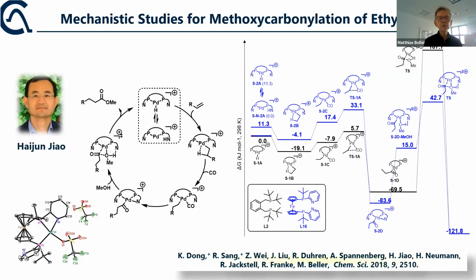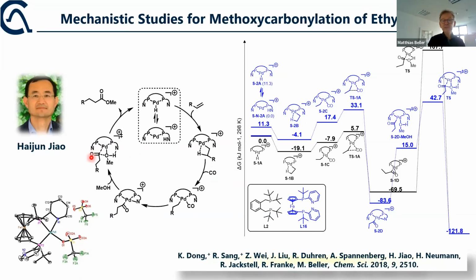On the one hand, it improves, of course, the deprotonation of methanol. This step, of course, but it also stabilizes the catalyst system. Additionally, it stabilizes both the metal zero particles as well as the corresponding metal hydride particles. And calculations showed very clearly that the metal hydride on the palladium is somewhat in between the palladium center and the corresponding amine. And in this way, it can also be easily transferred to the olefin.